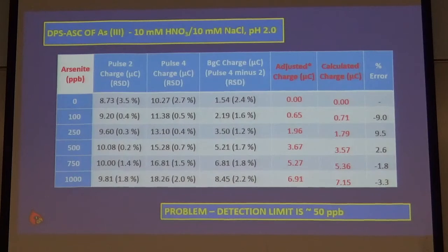Now, if you would go back, I'll show this slide again. For the blank, that signal had a little bit of a crescent there. The signal wasn't 0 for the blank. It was, in fact, 1.5 microcoulombs. But as you increase the arsenic concentration, the charge increases. That's good. The size of the crescent was getting bigger. But what we have to do is correct the 100 ppb charge for the background. And so the signal due to arsenic is the difference between those two charges. If we simply adjust by subtracting out that background, we get those charges which are due to the arsenic.